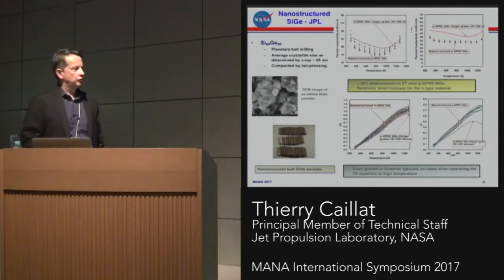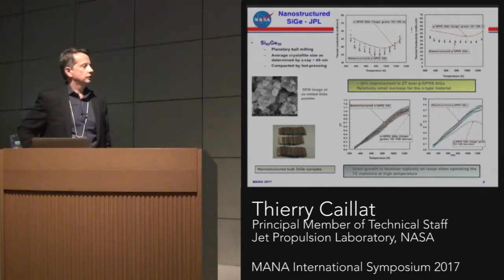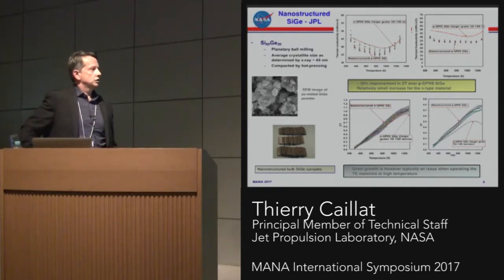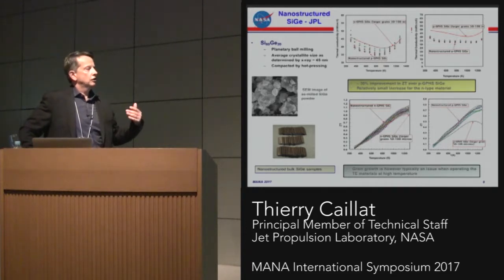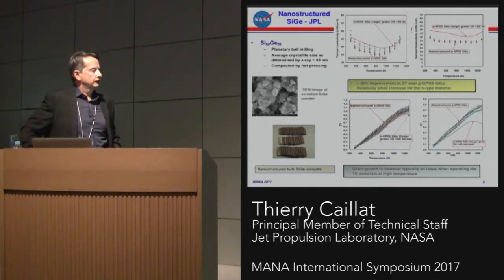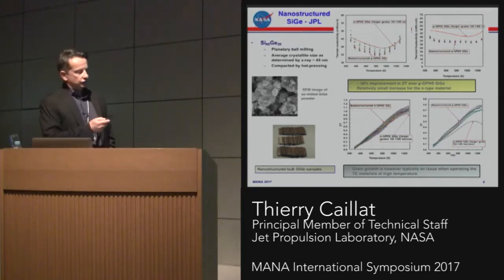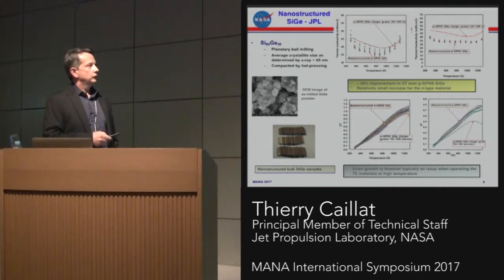We've done something similar at JPL with the materials that we are considering for space applications. For silicon germanium, we use a different approach, because typically we use bulk material. It's difficult to use with the heat fluxes that we're dealing with. You cannot really use thin films or any low dimensional type of structure. So we are aiming at something that's applicable to our type of RTGs, which are bulk materials. So we use a ball milling technique. If you do this right, you can achieve small crystallites on the order of nanometers.